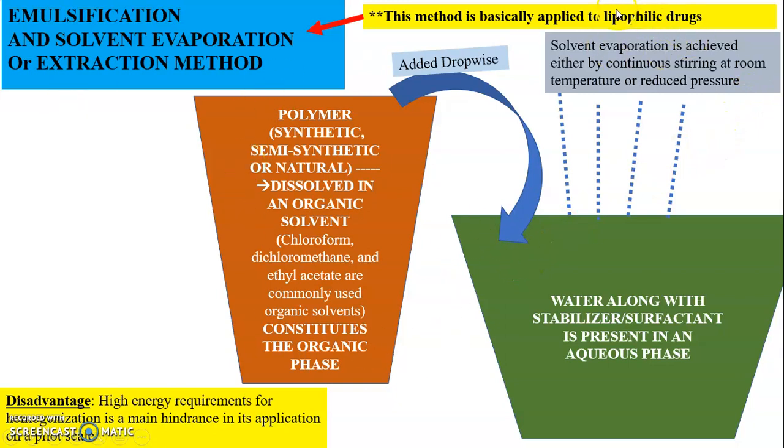So, here you can add this lipophilic drug directly into the organic phase, or you can disperse this lipophilic drug into the aqueous phase. Now, coming to the aqueous phase, it contains double distilled water or Millipore water or distilled water, as well as a stabilizer in the form of a surfactant, so that the formed nanoparticles do not adhere to themselves. Now, when this organic phase is added dropwise to the aqueous phase, there should be continuous stirring of the aqueous phase for the solvent evaporation, so that the phase separation coacervation can easily take place.